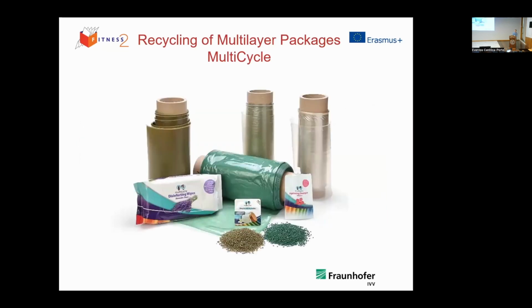And in a collaboration with Amcor, we have also shown that we can apply our films and our recyclates in new packaging materials. So the packaging on the very left, the disinfection wipes, contains recycled polyethylene. The packaging in the middle contains recycled polypropylene, and the packaging on the very right contains recycled polyamide, which were all recycled at a scale of 100 kilograms per day.